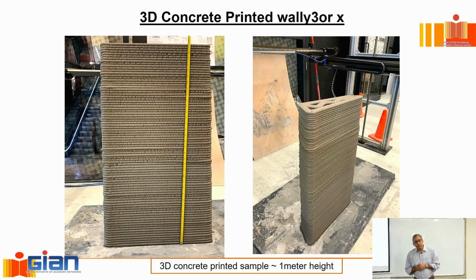Okay, what is fundamentally different is the way that this alkali activated binder paste would behave when you shear it. Now, what changes its behavior is all the silica that is present in the activating solution, right? Why do I need silica? I need silica to control my strength. Okay, if you are lucky and you're dealing with a source material which has highly reactive silica in a large content, then you don't have to bring in additional silica from the outside. Then you can just start working with this as if you're working with cement paste. Then half your problems are solved, right? But the minute you have to dose external silica, and usually that is brought in the form of sodium silicate. Okay. Now the question may be, some people do ask this: why sodium silicate? Why not nanosilica? Well, you could add nanosilica as well, except it's much more expensive.